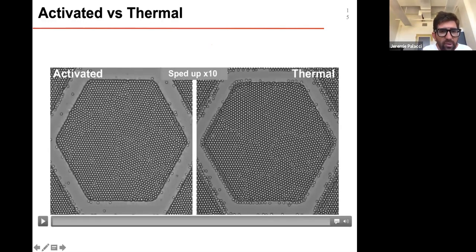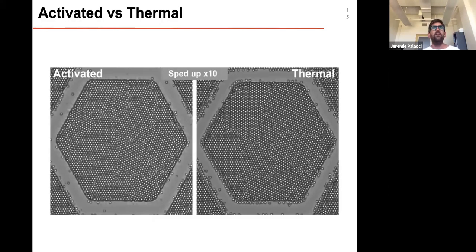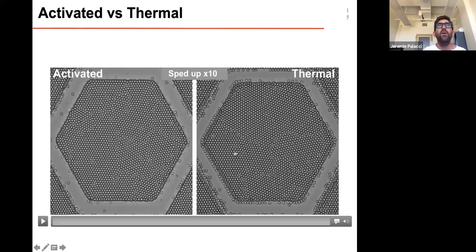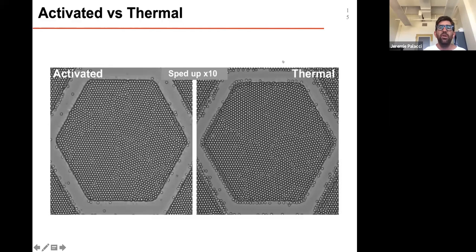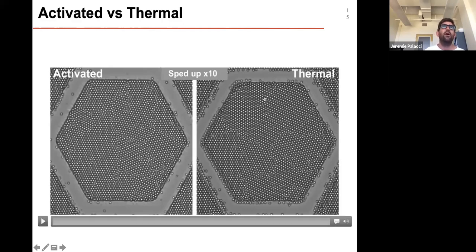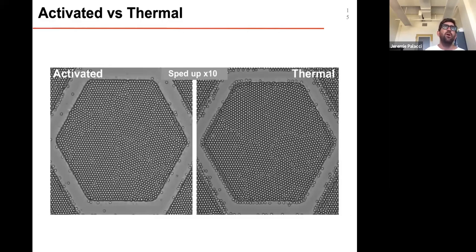But to answer the question, it's absolutely right. As I said before, you have those polycrystallites. The thermodynamic ground state is one large crystal. So if you wait long enough, it's going to happen. In the thermal state, it's going to take something like 12 hours. In our conditions, with a system of that size, we get a large monocrystal after 12 hours in thermal condition, and after 30 to 40 minutes or so in the activated state. Thank you for asking the question.